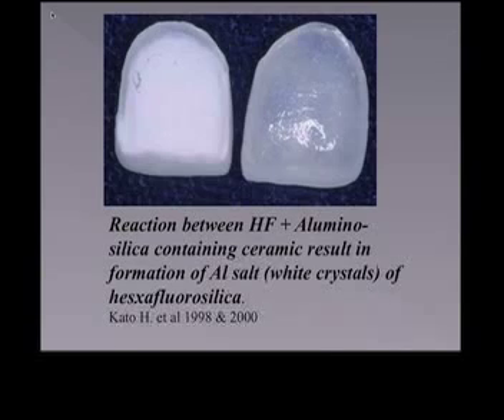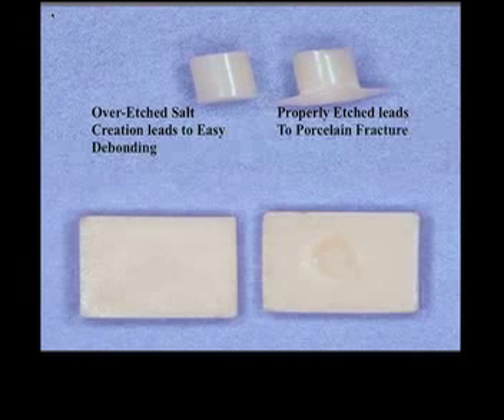And you can see that on the picture on the right. The tooth actually pulled away from the substrate. Very nice, strong bond. In the over-etch example, the salt interfered with the bonding, and it created a much weaker bond.